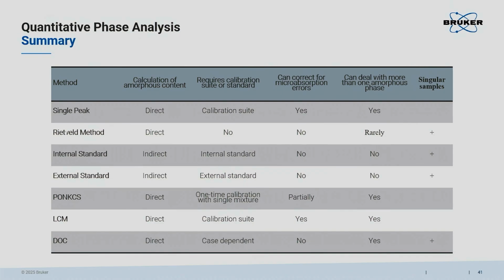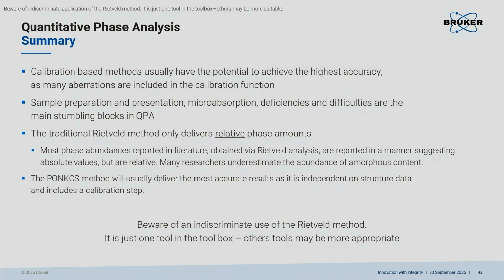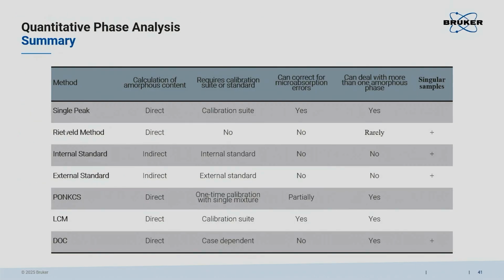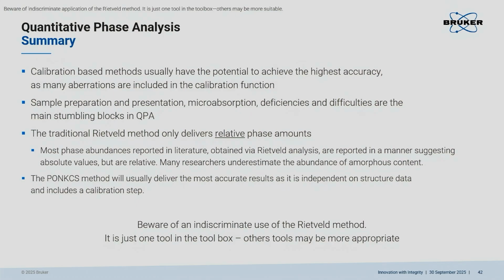Are there any methods which can deal with microabsorption? Yes, if you do a calibration. Always, if you do a calibration, you have a chance. The PONKCS can also do it, but partially. So I would rather say no than yes, but to some extent. And then, of course, the linear calibration method. Again, you are using a calibration function. You have mixtures with known weight, which you use to determine the calibration function. That can cancel out the microabsorption error. My summary: calibration methods usually have the potential to achieve the highest accuracy. Of course, you are calibrating out all potential errors, ideally.